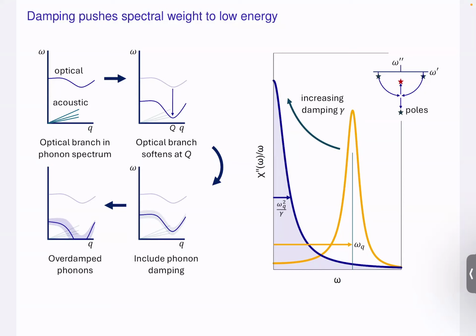So that's very long-lived. So with very high damping, modes actually become very long-lived. The overdamped modes have a very slow relaxation rate. Relaxation rate goes as effectively omega squared over the damping. So as damping becomes large, the spectral weight basically is shifted from up here to down there. So now you can, in principle, exceed that relaxation rate at a much lower temperature, is what I'm saying. In order to get effectively equipartition theorem response, the temperature would have to be here for an underdamped oscillator, but it can be down here for an overdamped oscillator.